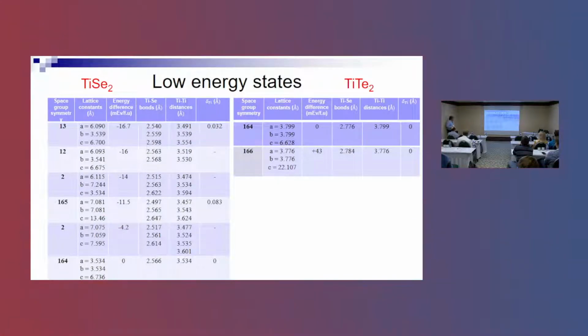What we see? In principle, at high temperature, the ground state has the space symmetry 164. This is the zero energy. This is what we name the disordered state. The state with charge density wave is not even present here because it's higher in energy. And we see that in the case of titanium diselenide, we have a lot of different minima with this type of symmetry, and this is the lattice constant. Basically, all of them are even lower in energy than this trigonal 1T structure, and they can be explained in terms of different types of charge density wave.